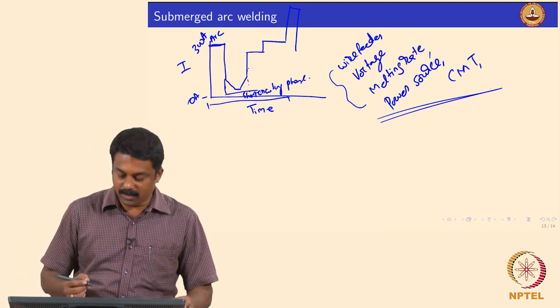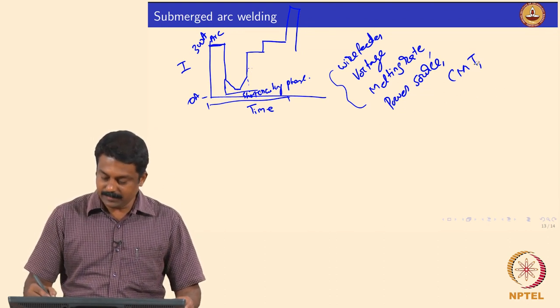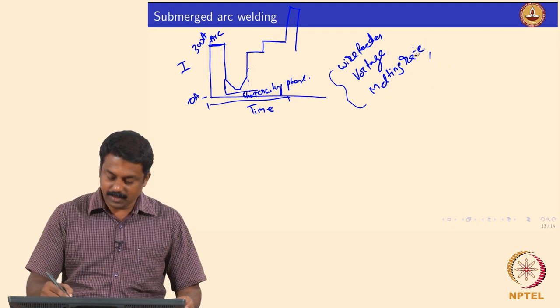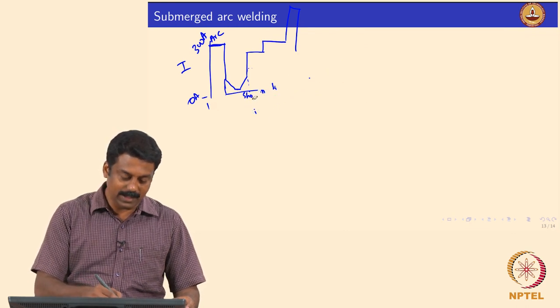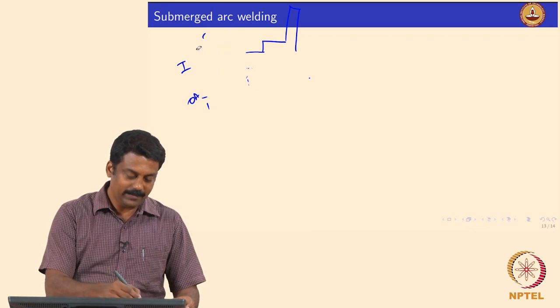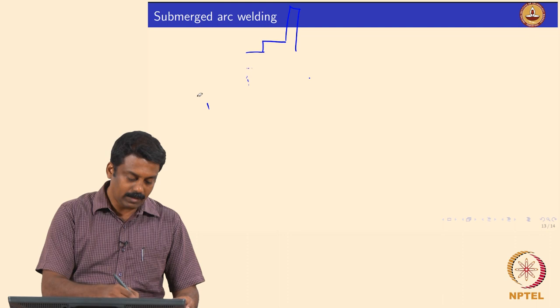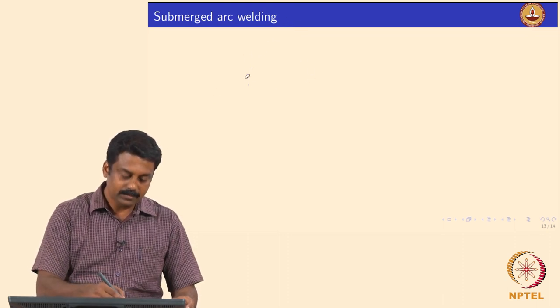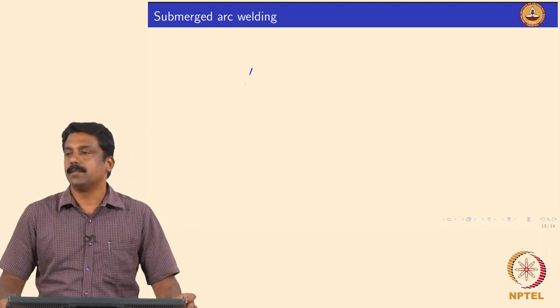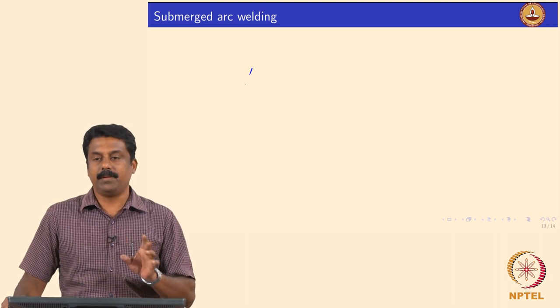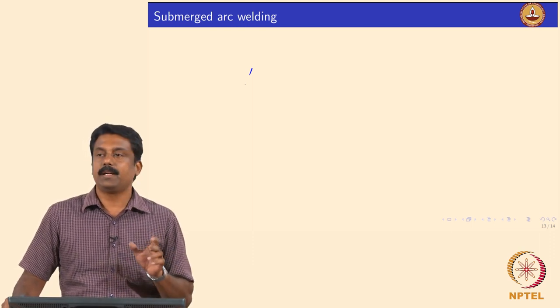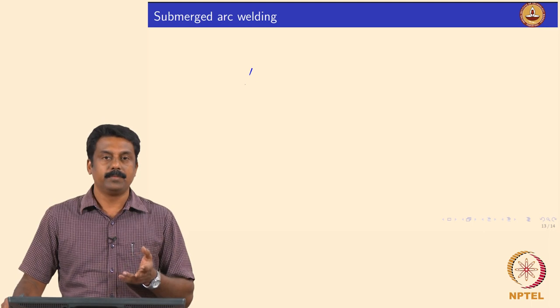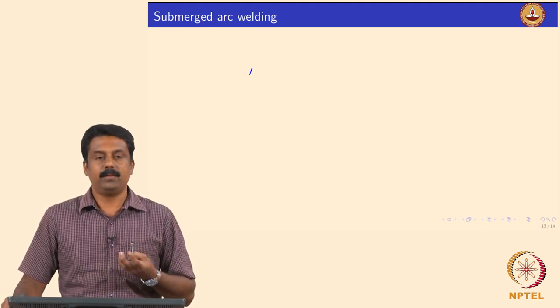So now we will move on to the last welding process in consumable welding: submerged arc welding. We used to have one very nice setup in IIT Madras, but unfortunately we condemned that setup. The process itself is similar to GMAW — the schematic and everything is similar. We use a consumable electrode without any flux coating; it is a wire electrode. Wire thickness is much larger than what you use in conventional GMAW — conventional GMAW is about 1.2 mm, not more than 2.2 mm — whereas in submerged arc welding we can use much larger diameters.